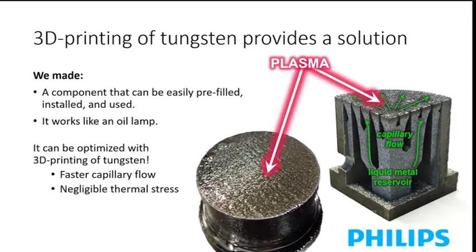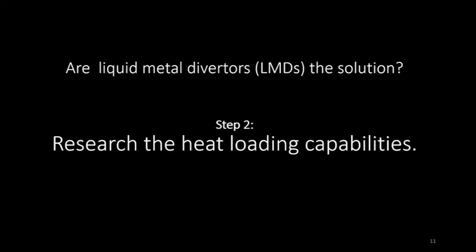And from that perspective, for those of you who are familiar with neutron loading, neutrons continuously degrade the materials in fusion reactors. That's a big problem. But we might wonder, actually, is that still a problem here? If the material has virtually no need for strength, does it matter if we lose a little? So that is actually very interesting. Side note here. All right, so we made a bunch of these samples.